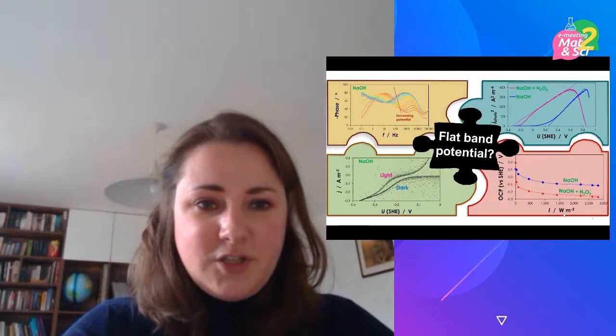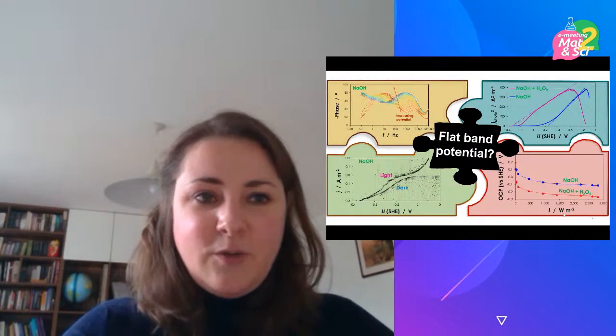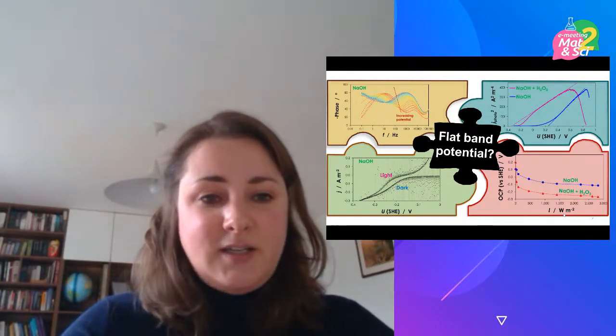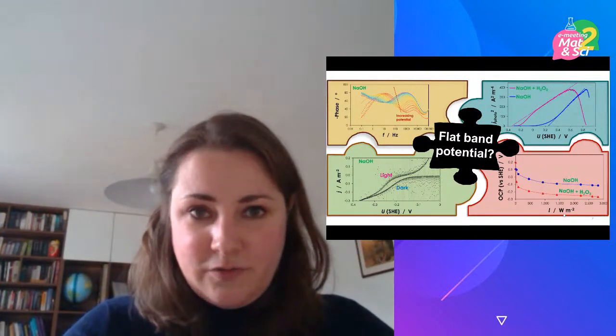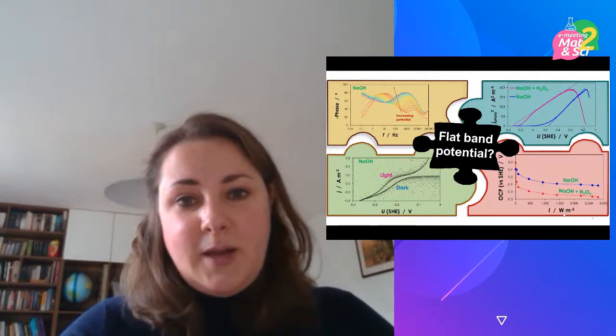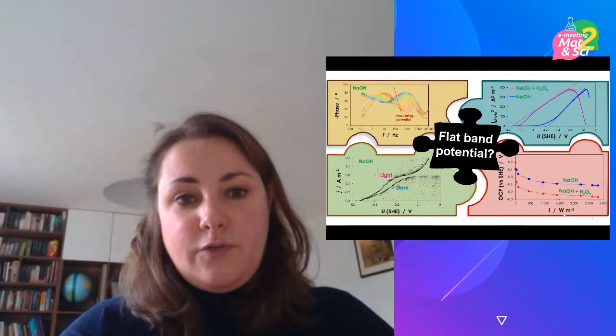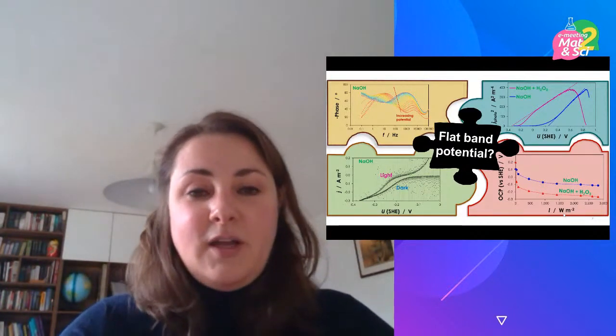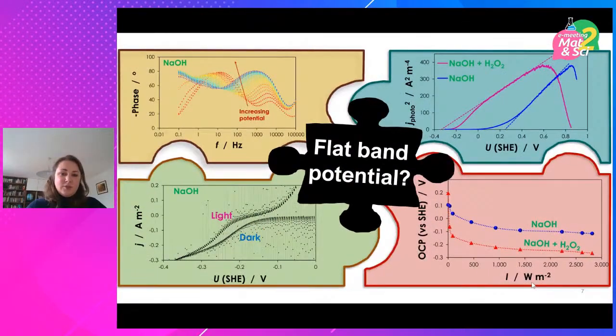So to resolve this issue, I embarked on a systematic study where I looked at the main techniques that had been mentioned in the literature for several decades for the measurement of this value. And then I applied them to a set of electrodes that I synthesized, and then I compared the results to try and understand what's going on.